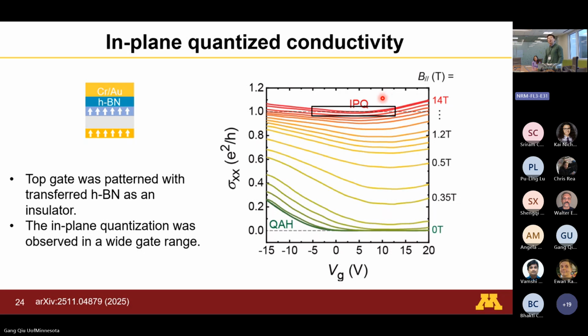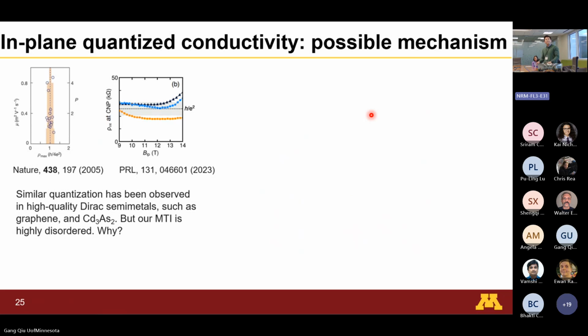But as you climb up to higher in-plane field, you pull the spin into in-plane directions. Somehow, this in-plane quantization happens, and it does not just cross this quantization value. It's actually parked at this number for a certain voltage range. So this tells us it's not a random number. It's a very reliable behavior, and we saw that in multiple samples. We call this in-plane quantization states.